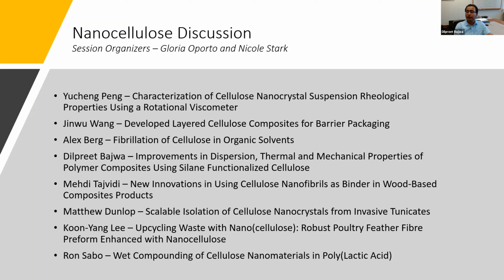So what we found through FTIR was that we were able to see in the samples that the silane groups were attached to the CNC, and through the FTIR, the characteristic stretching and bending vibrations were observed for the amine band. The second thing we observed was that under the TEM, the composite films with 1% PEO, 1% CNC and 1% silane showed the best dispersion compared to the formulations where the silane was either 2.5% or 5%.